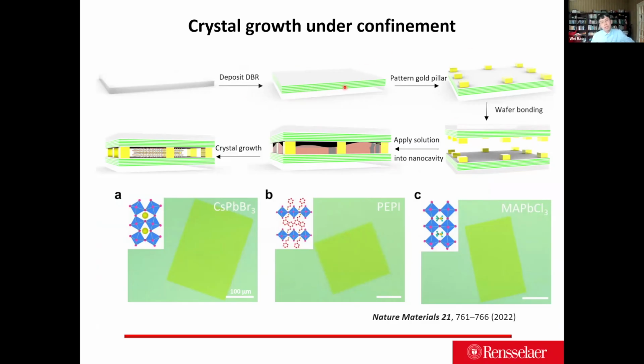The way we deposit them is by ion beam sputtering. It's what people who measure gravity waves use. They make really sizable big mirrors, and they can make the big mirror as flat as a super polished silicon wafer. We do the same method, and afterwards we pattern them with gold pillars using a shadow mask. The evaporation is done at wafer scale, and the whole wafer has a variation of about 1 to 2% in the gold thickness.